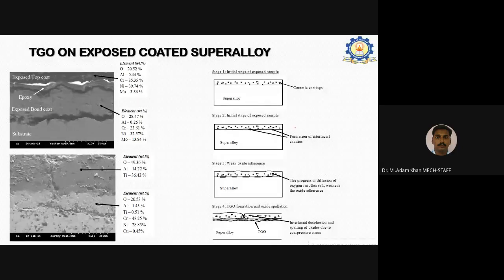At the same time, here you can see this is pure alumina titania. So alumina has come down and nickel has gone up. The transformation of nickel aluminide, some transformation like that, has reached a state to form TGO over a certain thickness. What happens when the TGO grows to the maximum? It will break my coating and it will spoil my component very fast. So that is the final outcome of the work.